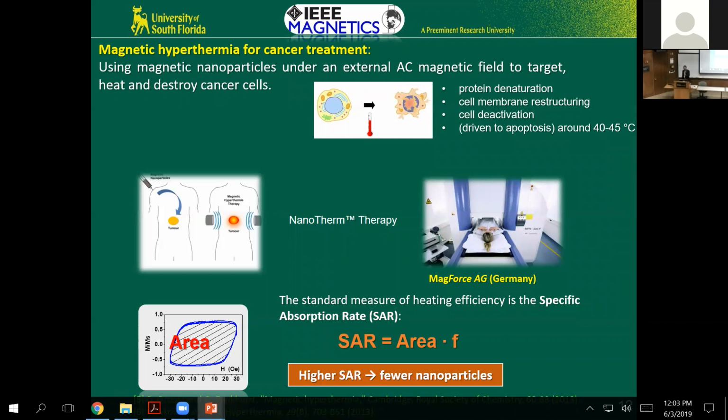I want to point out something very carefully. Remember, these are very small particles. We're talking about nanoparticles, and as you know, if you go below a certain size, most of them are superparamagnetic, so there's no hysteresis, isn't it? But that's the DC hysteresis. That's what you measure in a SQUID or a magnetometer. Don't confuse that with this hysteresis here. This is the AC hysteresis loop.